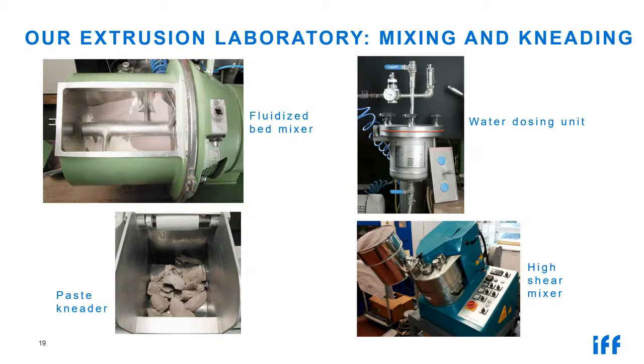Later on, after you have received a homogeneous dry mix, you spray water in, and the process is ended when you get small dumplings, very small dumplings, which you empty out of this container and fill into a paste kneader, which you can see left below. This is a typical kneader, which further plasticizes the mass before you put them into the extruder. Our water dosing unit you can see right above. This is a simple equipment, but very useful and precise.